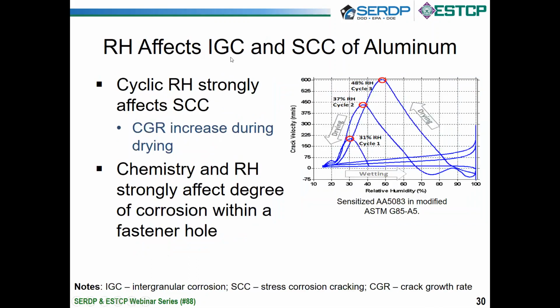Okay, next thing we wanted to look at was intergranular corrosion, stress corrosion cracking. This data is also from Luna Innovations, the team members there. To orient you, this is relative humidity, this is crack growth rate, and what we did was cycle the relative humidity going both directions. So Luna has developed some pretty nice sensors for measuring crack growth rates in situ. And what you see here is that as you cycle the relative humidity forwards, you're on this set of curves. As you cycle it backwards, you're on this set of curves.